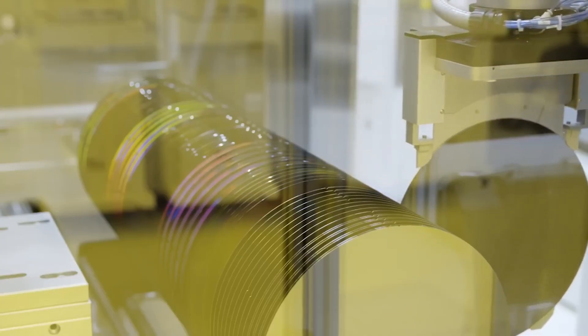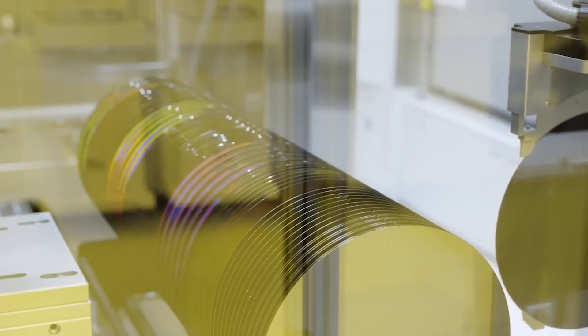But even after passing through this modern polisher, the wafers are not smooth enough, so they need to be polished again through a chemical process. The result is silicon wafers with a surface roughness of less than 0.1 nanometers, now completely polished.